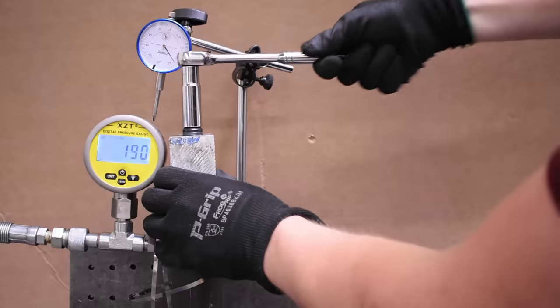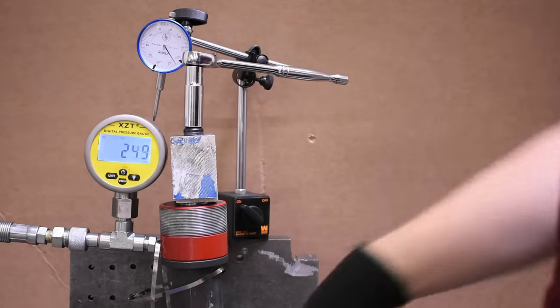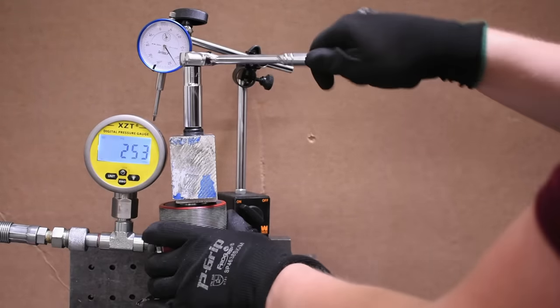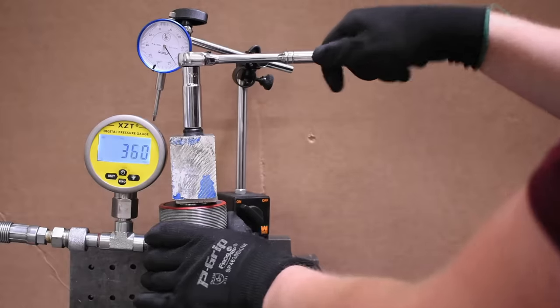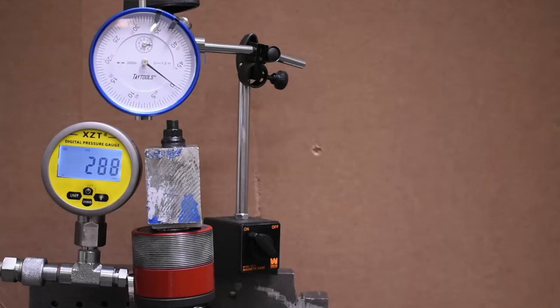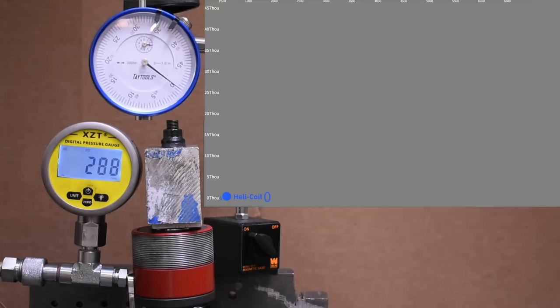Our L19 ARP stud started being measured for stretch at its torqued state of 3600 PSI. In case any of these let go before that level, we're measuring movement from near 0 PSI, or about 300 here. But we can see where these are at that 3600 PSI and sort of do the math coming up on our leaderboard to compare against the stud in just an original cast iron.